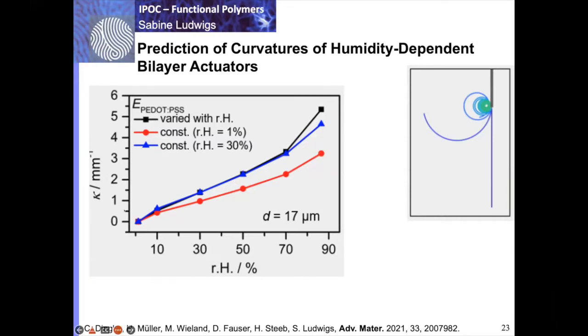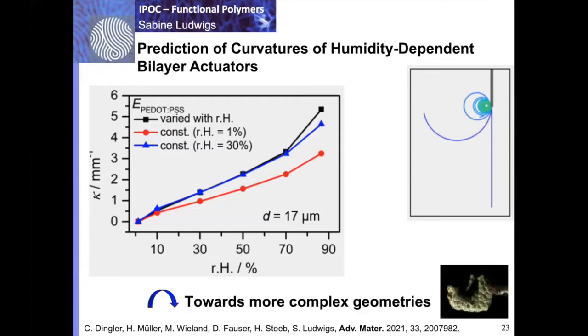Actually, it gets more realistic when we take the values of the elastic moduli taken at 30%, so at ambient humid conditions, or if we use the values which are varying on the relative humidity, as you see with the black points here, then it's even giving more realistic values, and then we get also higher curvatures. And that's for a 5 millimeter actuator, the prediction how the rolling up of the bilayer would work.